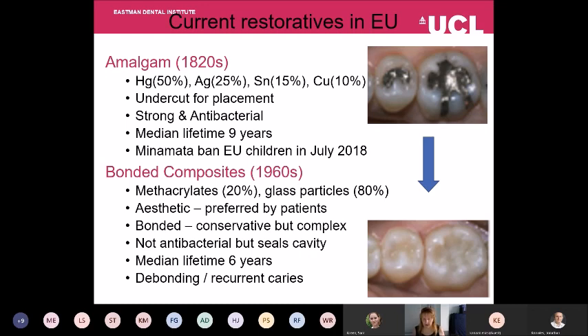The alternative that's been available since around the 1960s is the bonded composite. This consists of around about 80% of very fine glass particles that are dispersed in polymerizable liquid methacrylates. What you get is a paste that when you expose it to blue light, it sets solid. It's much preferred by patients because of its aesthetic appearance, and it's bonded to the tooth. Because you get bonding, it's more conservative of the tooth structure, but the bonding procedure is really complex. The composite is not antibacterial, but what it does is it seals in the bacteria.